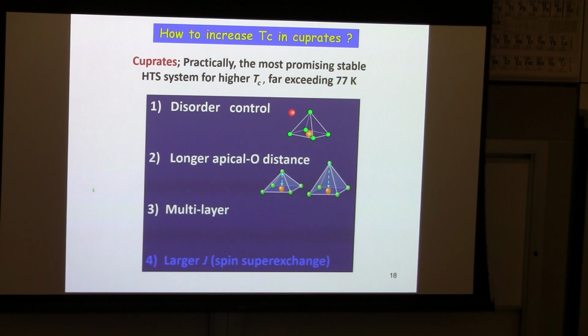But the 98 is far below the world record of the mercury-based cuprate. And also, second one, many people know that one of the important factors that influences the TC value of the cuprate is the apical oxygen distance from the copper plane. Many people believe that a longer apical oxygen distance is better for the higher TC. But unfortunately, we did not know how to increase the apical oxygen distance by controlling some element or combination of elements. So this is no effective way in real material.